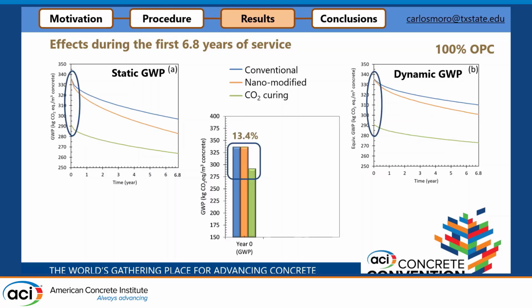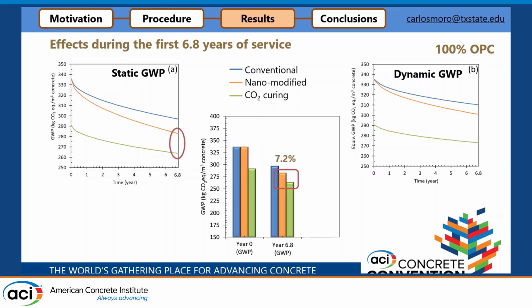Okay? So at the beginning, the blue and the orange one have 13.4% more CO2 emissions than the CO2 curing. Why? Because the CO2 curing already uptake some of the CO2. Okay? At 6.8, we see that the static, if we compare orange with green, the decrease was 7.2%. But using the dynamic, the difference was higher.